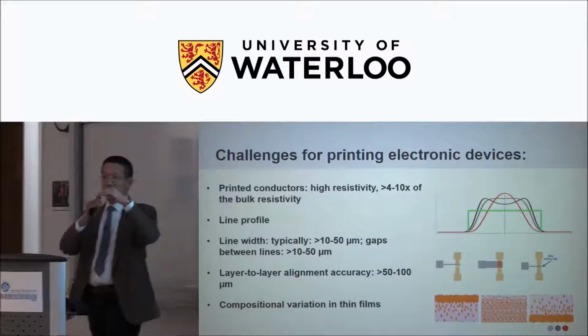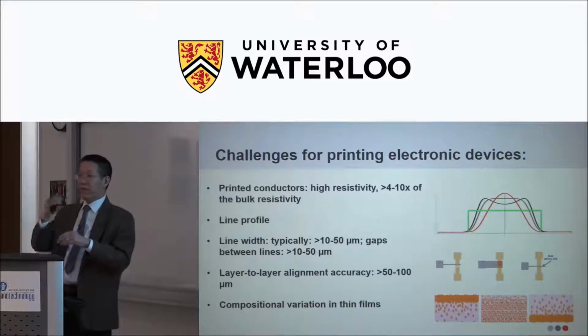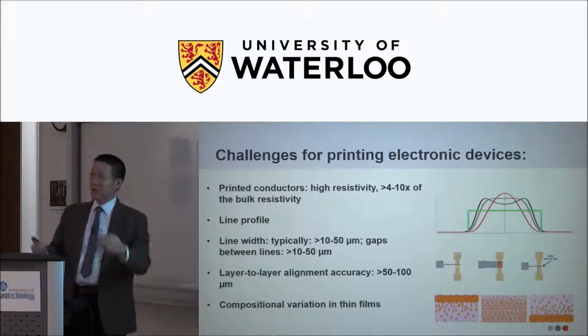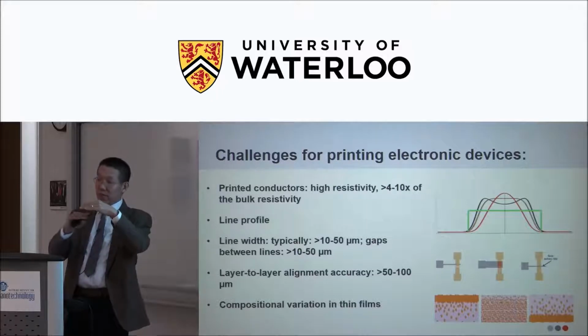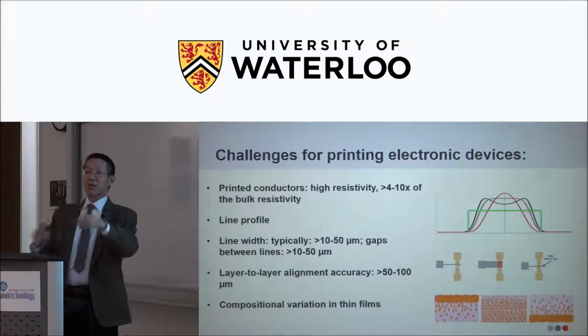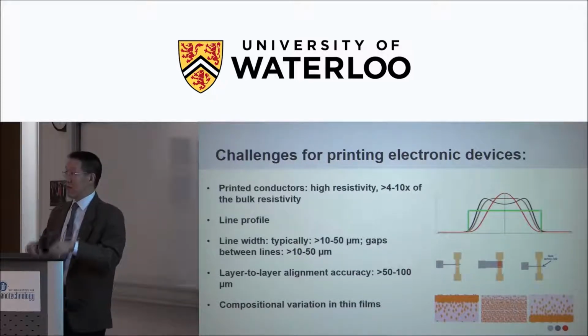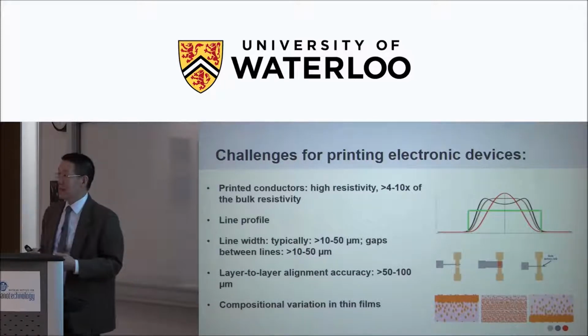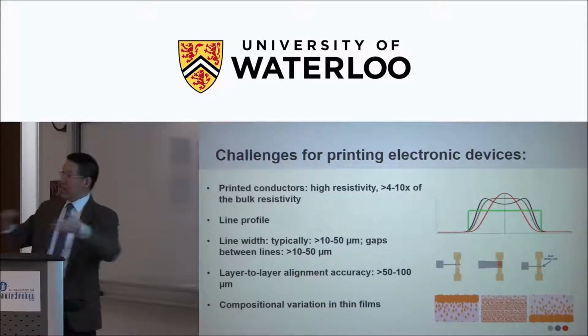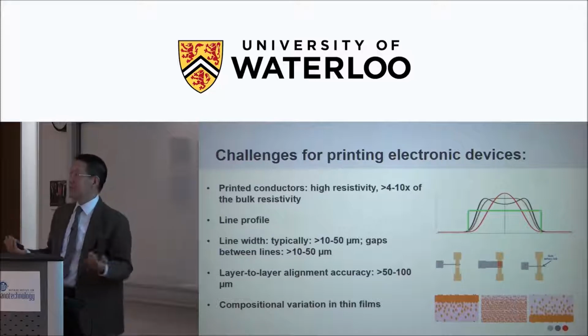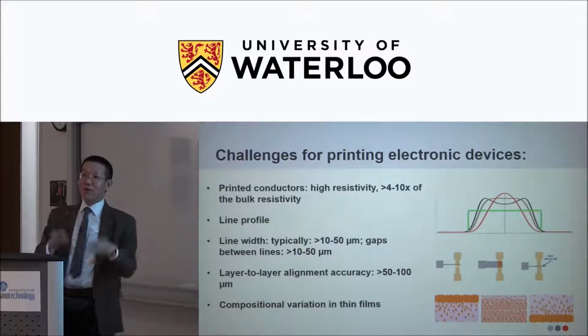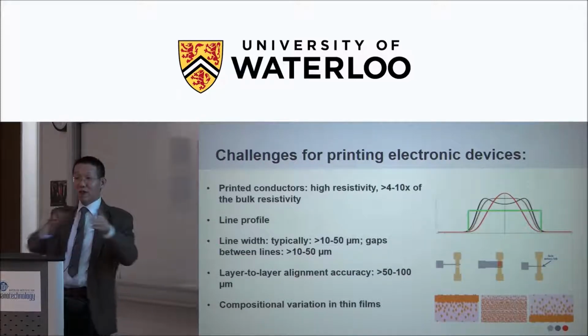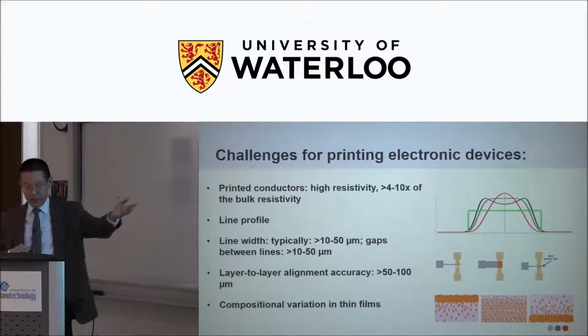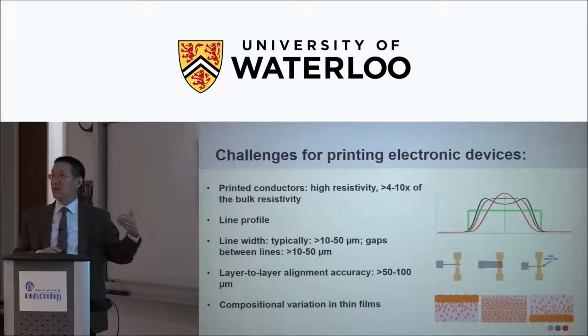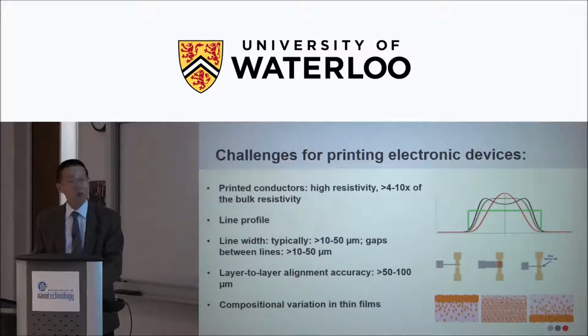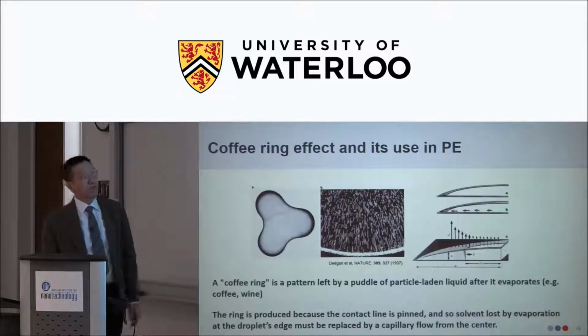But in most of these inks, there's a phase separation when it dries. The bottom layer is typically more resistive, actually. So when you do the transistor measurement, you have to reformulate the ink, right? Because they are meant for lateral conduction. Traditionally, they don't care about the vertical direction. They want to have the passage around the surface. So those things present challenges when we make organic semiconductor or printed electronic devices.